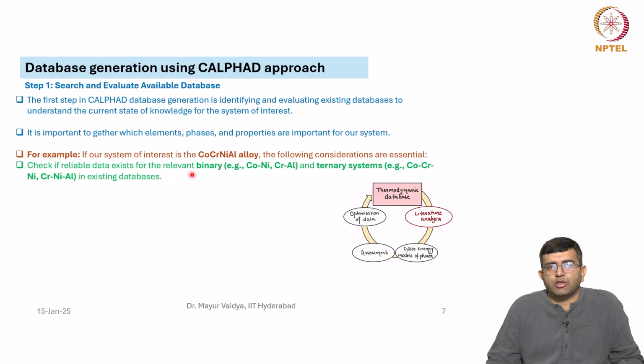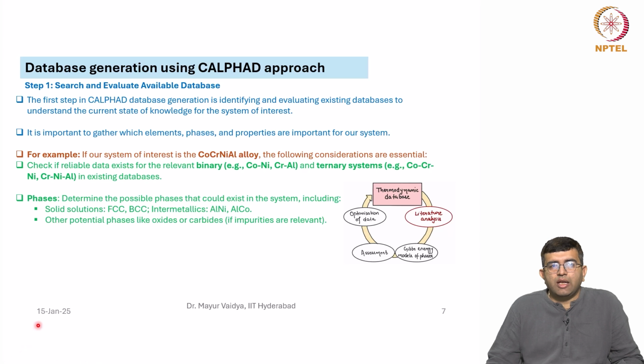reliable data available for the binaries. That means cobalt, nickel, chromium, aluminum, and ternary systems like Co-Cr-Ni, Cr-Ni-Al in the existing databases. Then what are the possible phases that could exist in the system, including solid solution phases like FCC, BCC, intermetallics, Al-Ni, Al-Co, and other potential phases like oxides or carbides if impurities are relevant.